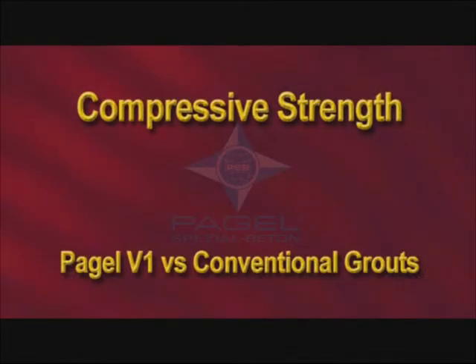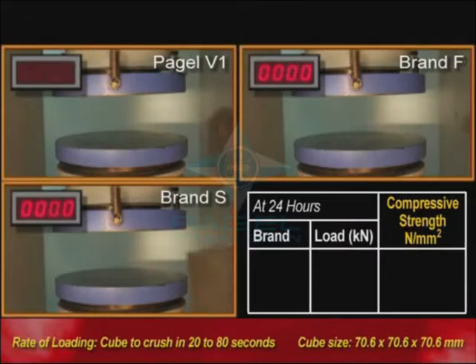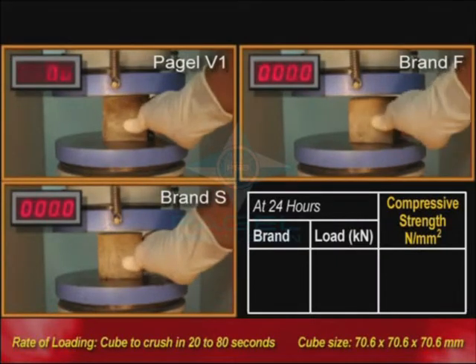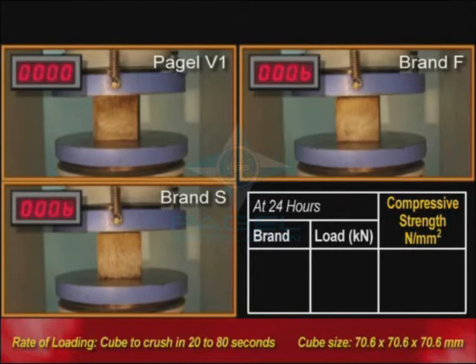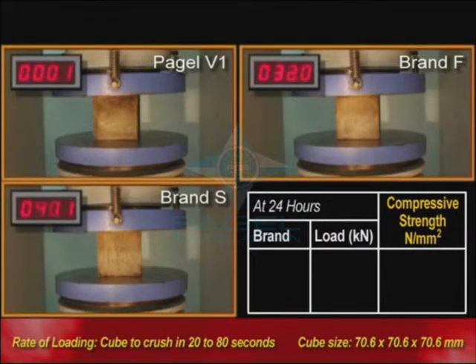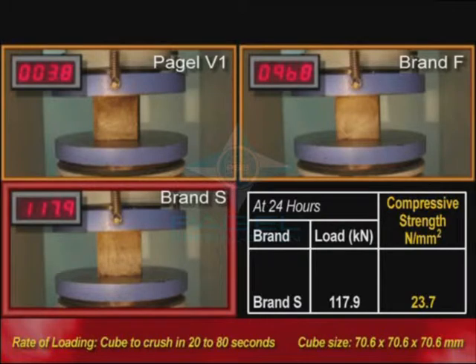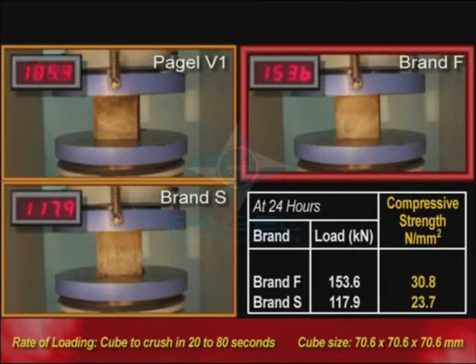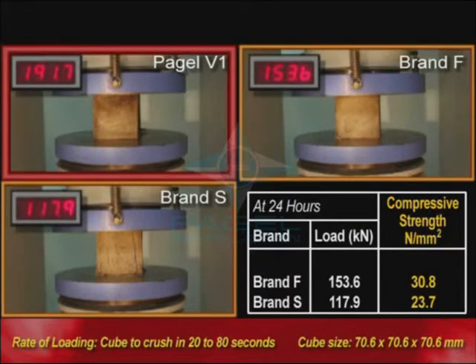One of the most important properties for a grout is its compressive strength, which we will first test on blocks that have been cast only 24 hours ago. As we see, the grout of Brand S cracks at 23.7 Newton per square millimeter. The grout of Brand F has a compressive strength of 30.8 Newton per square millimeter. However, the block of Pagel V1 grout can withstand 38.5 Newton per square millimeter.